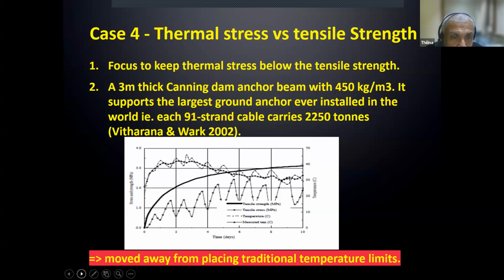In the top graph, the darker one is the tensile strength, and the bottom wavy one is the thermal stresses near the surface. In this case, I think the daytime temperature hit 35, at night 15 degrees. So what we did is at night, in the evening, we put on plywood to keep the differential temperature down. In this case, all the thermal stresses are below the tensile strength. So it never cracked, and we were very happy. Otherwise, we can't put that much reinforcement, we already had reinforcement, and the chances of cracking should be limited even if we had reinforcement, because of the nature of the beast. If one of our anchors gives way, that will break the dam in half. Next one, please.